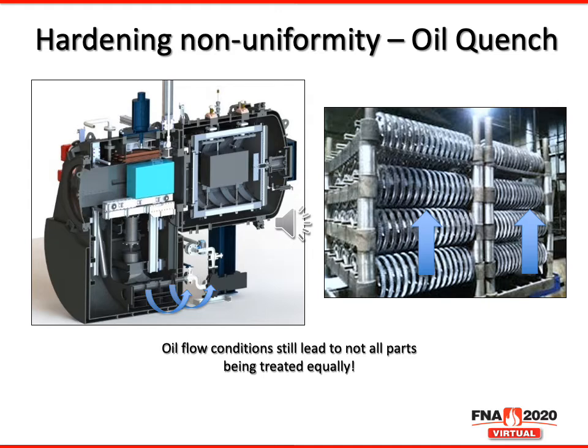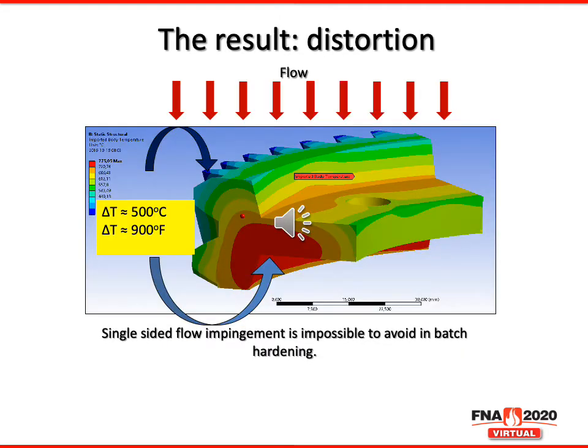Also, in this case, even though it's a low vapor pressure oil, there's still the concern and possibility that vapor bubbles will form around the parts as they're being quenched because of the rapid boiling occurring. Of course, the furnace is built with features to mitigate that formation of vapor, but it doesn't stop it completely, and of course that will also slow the heat transfer rate. This flow variation results in different surfaces of a single part cooling at different rates. When this happens, an internal temperature difference between one surface of a part to another occurs.